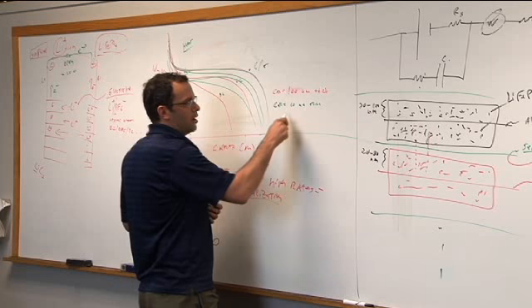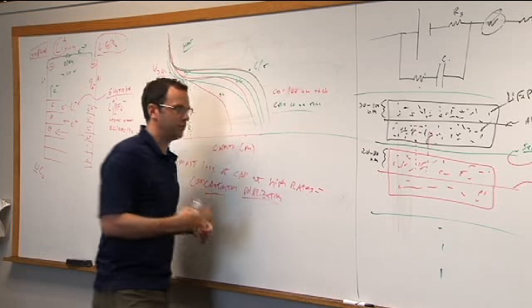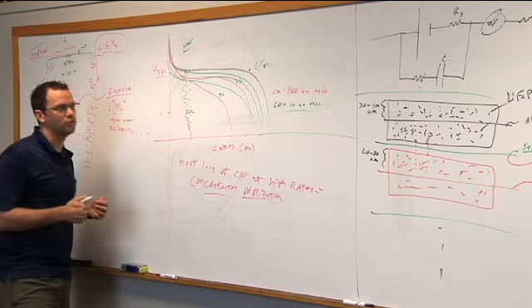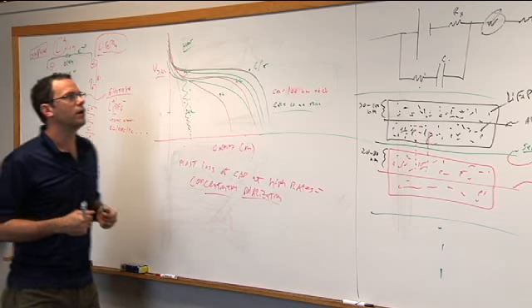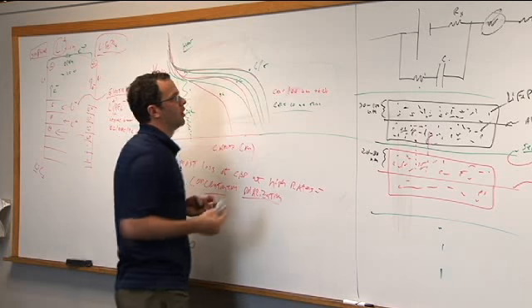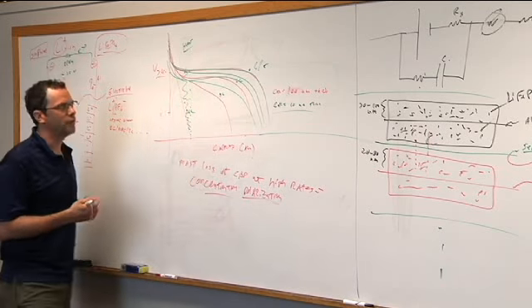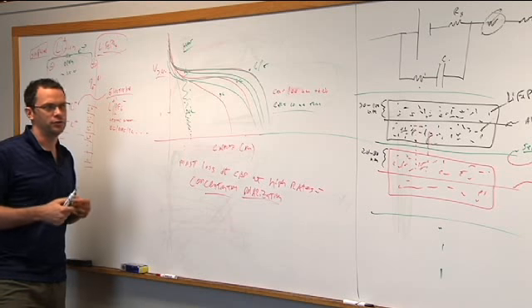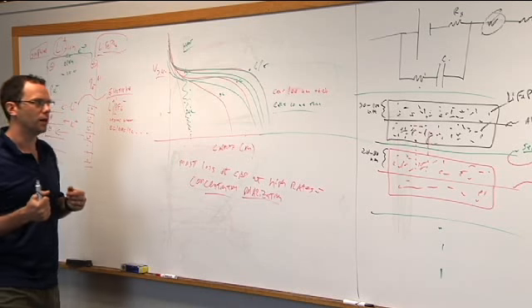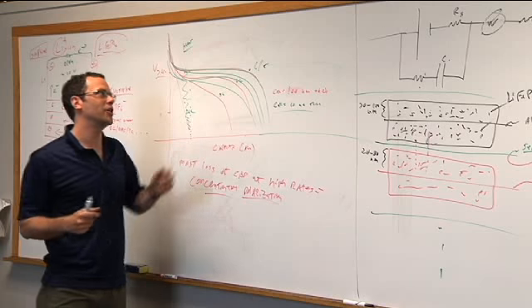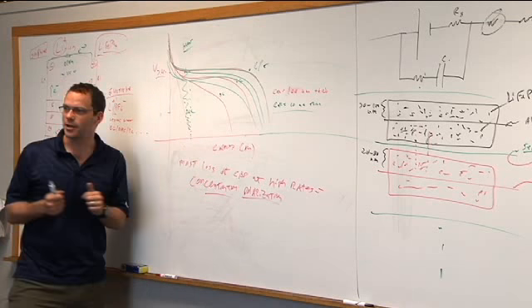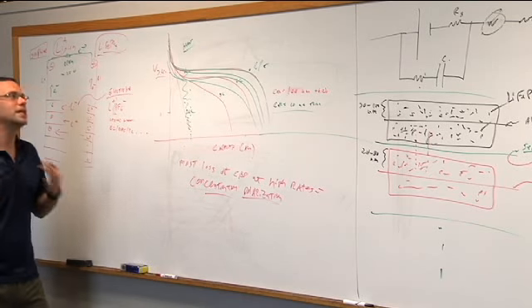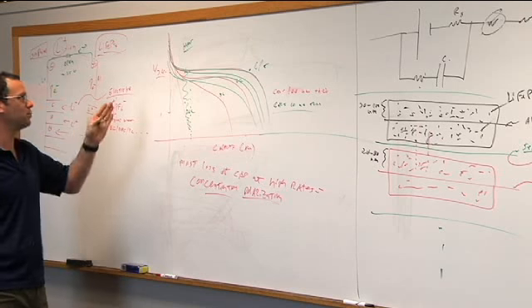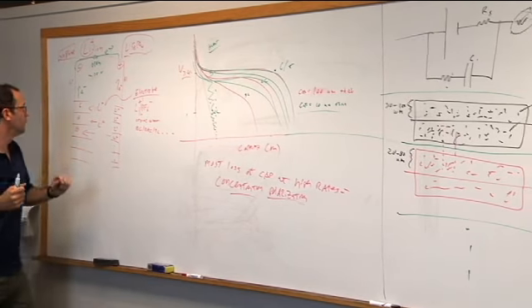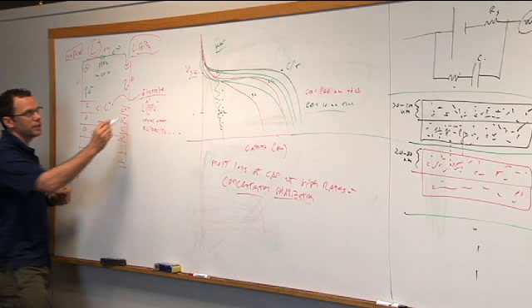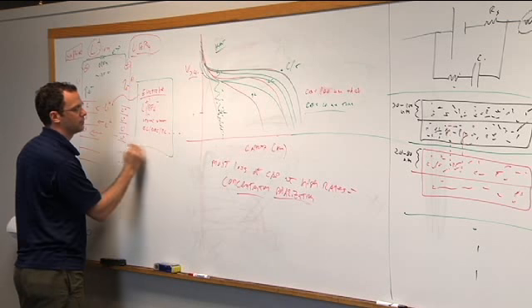And you know, the 10 micron thick batteries, they don't even make them, but if they did, they would be thousands of dollars a kilowatt hour, right? If you make 200 micron, 300 micron thick electrodes instead, you can get down into the $100 to $150 per kilowatt hour cost point, but you can't discharge it anything faster than a 5 or 6 hour rate. And if you do, you end up heating things up. So this gets me to the last point, and that is, why is heat bad? Heat is bad because of the electrolyte, right?